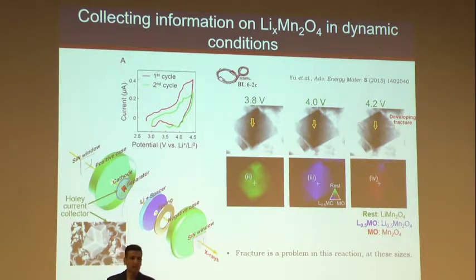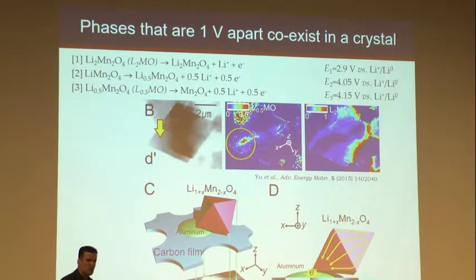Because we're doing imaging, we're also getting morphological information, and in this case, it was interesting to, again, locate areas where the particle was fracturing and opening up enough that we could tell that it was fractured. So now you can start making correlations between mechanics and chemistry in these kinds of systems. The other really intriguing thing that we found here was that by doing the reaction under working conditions, we started seeing states that you wouldn't really predict are possible. And so just slowing down for a minute and telling you what this material does.